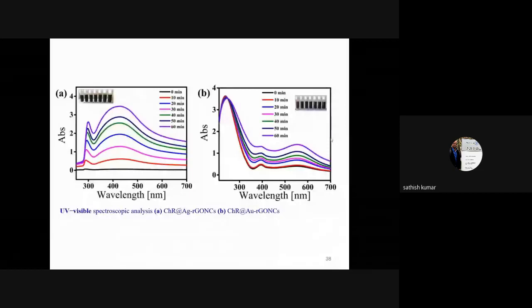So here we have clearly confirmed the presence of nanoparticles through the SPR phenomenon that I have explained in my previous slide. The peak located around 430 nanometer clearly indicates the presence of silver nanoparticles, and the peak around 560 nanometer clearly indicates the presence of gold nanoparticles on the surface of the nanosheets.